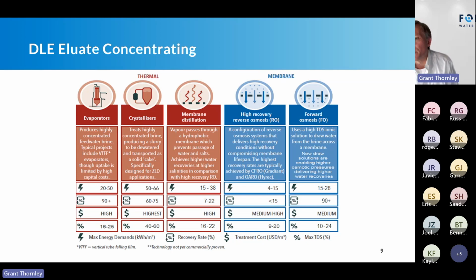The challenge with RO is that they are osmotically limited, meaning that you can only take the TDS so high. What restricts it is that the osmotic pressure will restrict the TDS from going any higher. So for example, for seawater desalination, which is TDS between 35,000 to, let's say, 40,000 ppm, because of the high TDS, you have to have significantly higher pressure. So you operate around 1,000, 1,200 PSI.